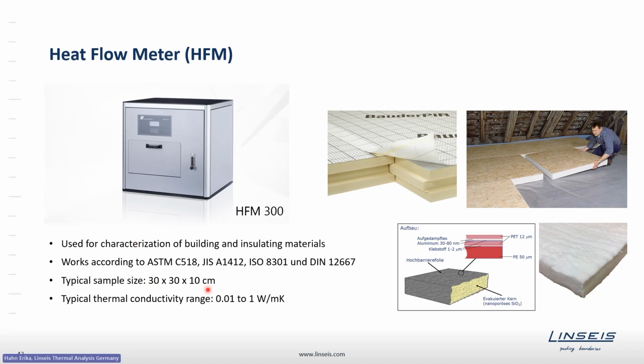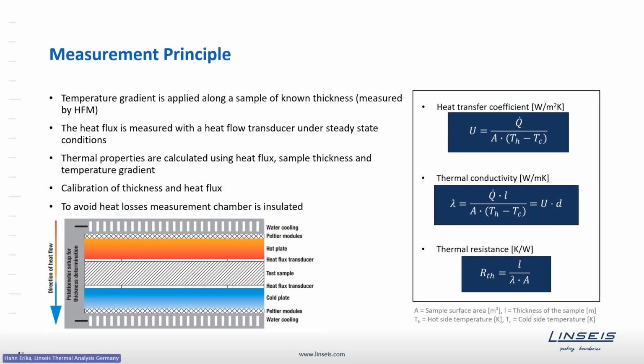And here the sample, as it is a building material, typically larger samples are required. A typical sample size is, for example, 30 times 30 centimeter with thicknesses of 1 to 10 centimeter. The measurement principle is basically similar to the one I have shown already for the TIM tester, where we have the two plates. One of them is heated up and the other one is cooled, so that we have the temperature gradient over the sample, establishing a heat flow. We wait until the heat flow is constant, so in the steady state.